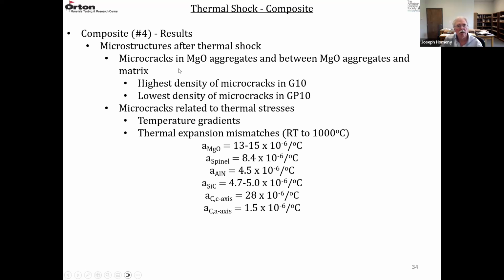So, microstructures after thermal shock. While there's microcracks in the MgO aggregates and between the aggregates and the matrix, the highest density of microcracks in these MgO aggregates was in G10. And then as we went up in pellet content, the density of the microcracks in the MgO aggregates decreased. So the lowest density of microcracks in MgO was in GP10. So the microcracks are related to thermal stresses due to temperature gradients or thermal expansion mismatches. We talked about both of these at the beginning of the course.